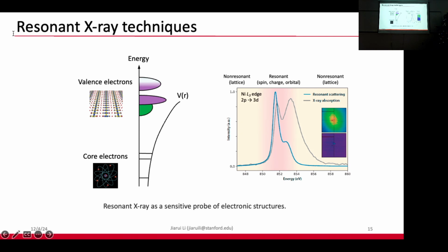And as you look at this black gray line, this records how much the X-ray is getting absorbed by the material. And you do see an enhancement of this X-ray photon and electron interaction when the energy is sitting at this resonant edge. This corresponds to the photons getting absorbed by the electrons and transitioning the electrons from the core level, 2p level, into the valence band. And we can also look at the other channel, the resonance scattering channel.